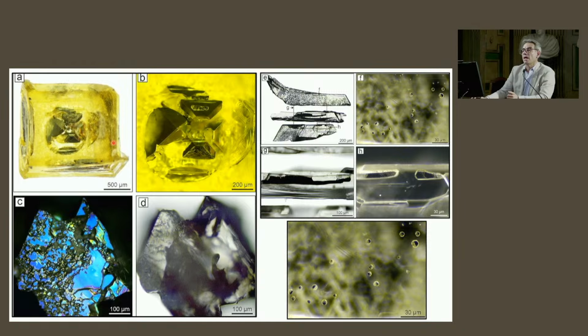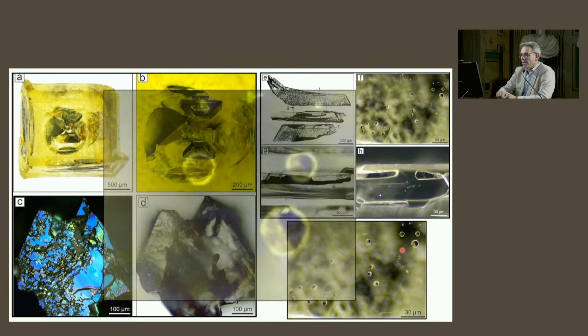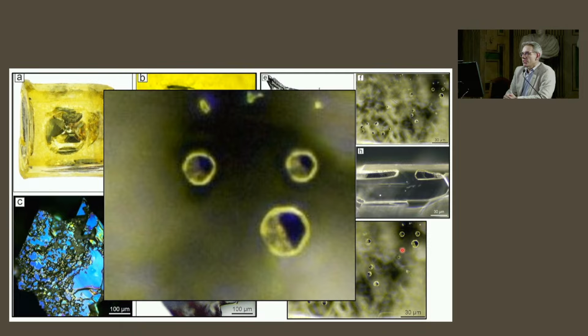They are relatively large, and of course I cannot give you a lot of information about this, but I can say that you can see huge inclusions in this diamond. Of course these are not quasicrystals because they are incredibly huge, 200 microns. But if you look carefully at these other inclusions, something like these spherical droplets here, look at the blow up here. There are inclusions which are actually composed of two phases. And the metallic blackish phases turned out to have compositions which could fit what we were looking for. So this is what we are doing in these days.